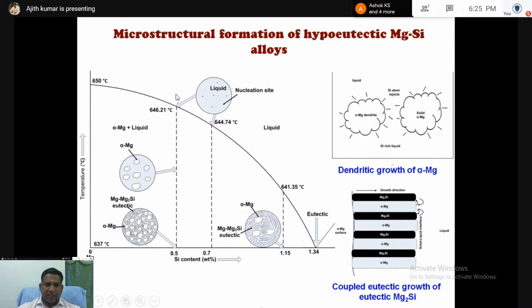Then if you see, 650 is the melting temperature of magnesium. When it reaches 646.21 degrees centigrade, that means for 0.5% silicon, it starts solidification. Initially, the alpha Mg will solidify, the remaining is liquid. Then the alpha Mg will grow like a dendritic kind of structure that we can see here.